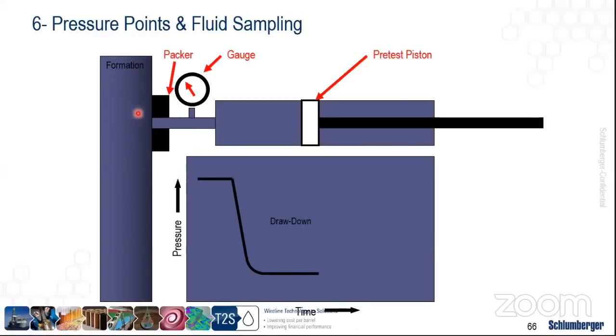So typically what would flow from the formation into the piston, into the vacuum itself, in this case, would be the invaded fluid. It would not be the virgin formation fluid, because it's a very small compartment or a very small volume that we actually move into. And it's typically around 20 cubic centimeters. In this case, we are just assuming that whatever response is coming from the formation deep inside is the same as what we have in the invaded zone.